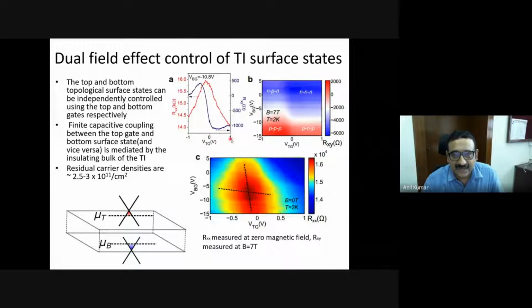This is just to give you more information. Look at here, you start varying the top gate voltage, and for a given back gate voltage, you get this kind of curve. Like this, for different back gate voltages, if you extract the curves, finally I can make a two-dimensional picture with the variation of the top gate voltage and the variation of back gate voltage. So there are 1000 such graphs embedded into this one. Now I have a PPP region, NNN region, PNP region, NPN region. If I apply a top gate voltage of 0.5 volt and a back gate voltage of 12 volt, I will definitely hit a PNP junction.